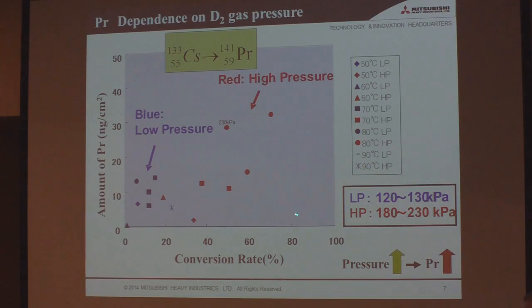This is a figure for praseodymium dependence on D2 gas pressure. In this case, we focus on the transmutation of cesium to praseodymium. This line means the conversion rate. Conversion rate means how much of the cesium was transmuted to praseodymium. And this axis means the amount of praseodymium, nanogram per square centimeter. The blue points correspond to low pressure. Low pressure means about 1.2 and 1.3 atm. And high pressure corresponds to 1.8 and 2.3 atm. As you can see, the high pressure region has a large amount of praseodymium and a high conversion rate.